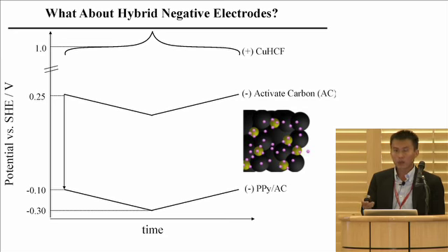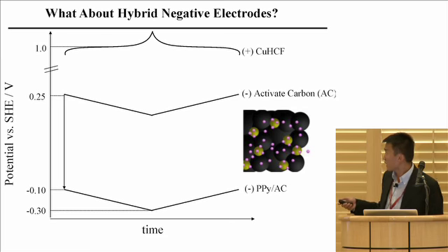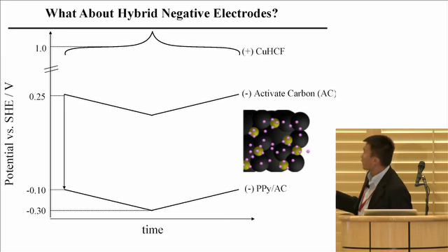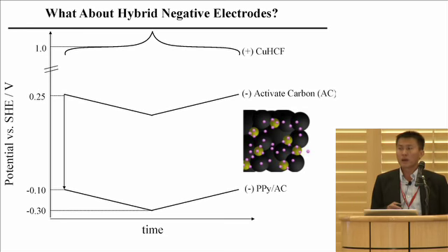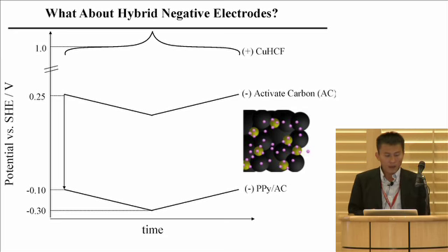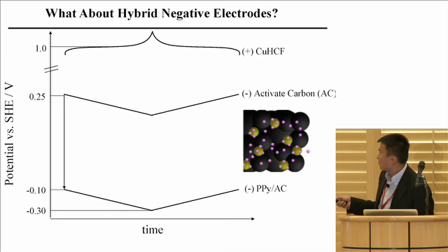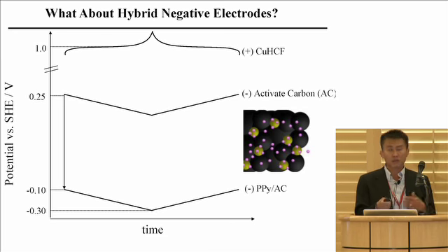Very fast, potentially long cycle life. We actually proved that we can do a long cycle life, 1,000 cycles without decay. So this is still going. And also, you might ask the question, let me use one last minute to talk about this. Why don't we also design the open framework structure, having the right potential for the negative electrode? We actually took this challenge, and a postdoc in the group, Maura Pasta, came up with this really great idea, and now replaces iron with manganese, playing with the synthesis.